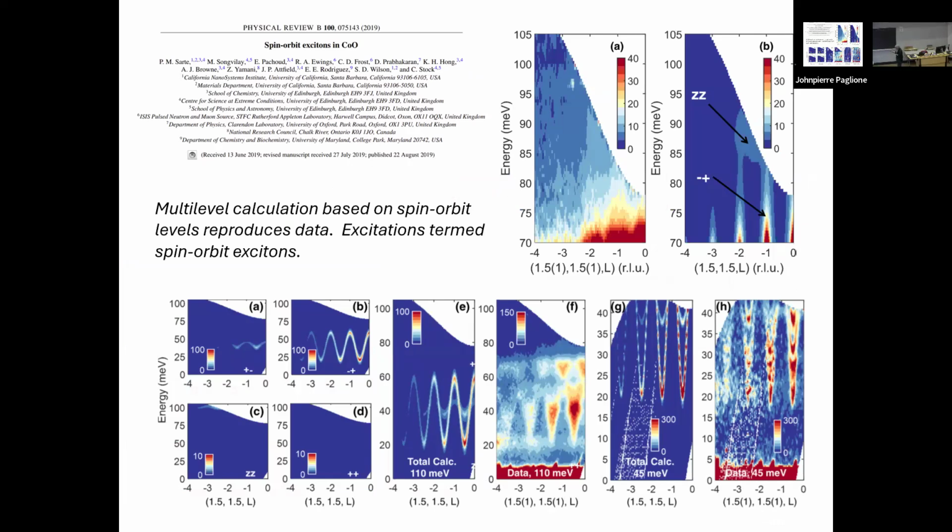So this is a summary of our excitations compared to the data. Immediately when you do this, you come up with the experimental gap in the excitation spectrum that corresponds to this anisotropy. But interestingly, you also get this diffuse stuff up here, which comes about in the RPA. And these are those amplitude types of excitations. It's just too bad they live up at 90 millielectronvolts, so you can't really control them.